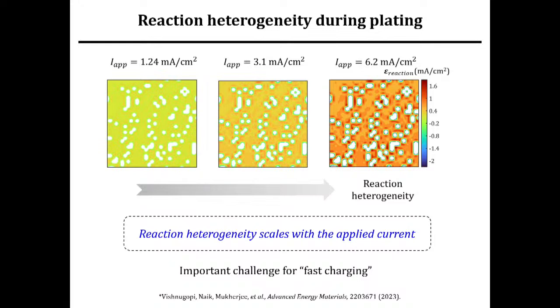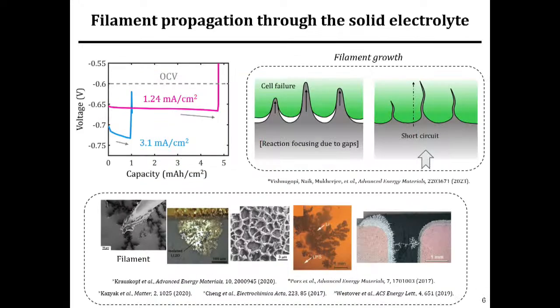In order to achieve fast charging conditions, the regime we want to be in is high plating rates. However, as we see here, reaction heterogeneity significantly exacerbates under such regimes, resulting in hotspots or reaction focusing areas that can lead to the onset of lithium filament growth, potentially resulting in an internal short circuit.